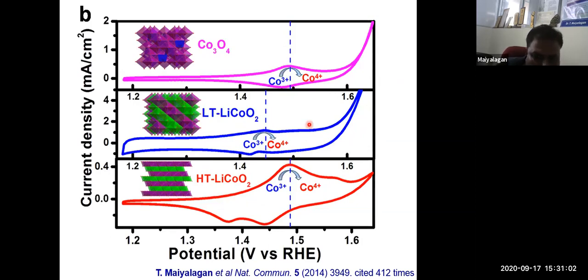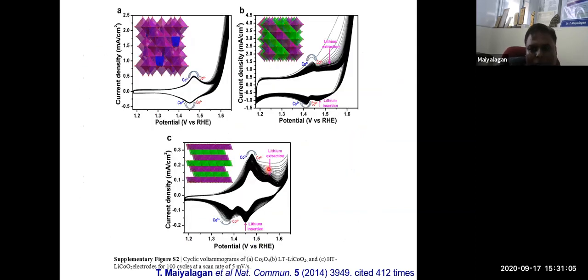So what happens? That is at 10 millivolt scan rate. We want to reduce the scan rate of the cyclic voltammogram to 5 millivolt per second to see what's happening, the peaks at the 5 millivolt scan rate. So this is a spinel structure, cobalt oxide, you dope lithium, and you retain the spinel structure. It's called low temperature. So this is a 3+ to 4+ and 4+ to 3+ cobalt. So lithium insertion and extraction takes place, and this is a layered structure where you can see this peak is very predominant. This peak is higher compared to this peak. This peak is not higher. This peak is due to the layered structure, lithium insertion and extraction.